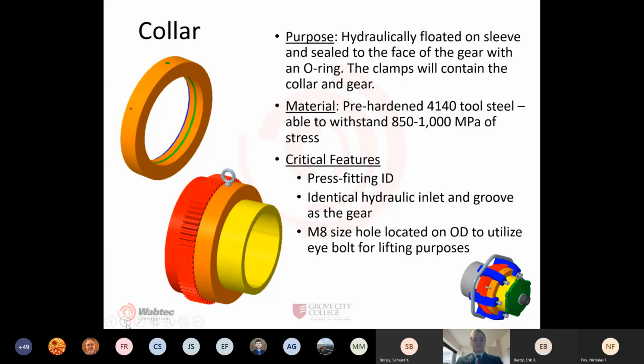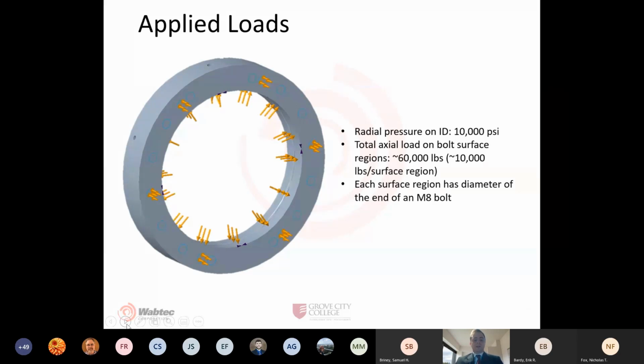In terms of material, the collar will have very high stresses, similar to the sleeve, so it will be made out of the same 4140 steel that the sleeve was made out of, again with an estimated yield strength of 800 megapascals. When setting up analysis for the collar, a 10,000 psi pressure load was applied to the inner diameter, which simulates the pressure of the hydraulic fluid. In addition, the total axial load caused by the clamp bolts is 60,000 pounds, which equates to around 10,000 pounds per bolt surface region. The surface region size has the diameter of the end of an M8 bolt, which is what is being used for the clamps.